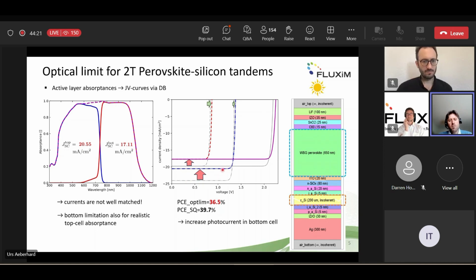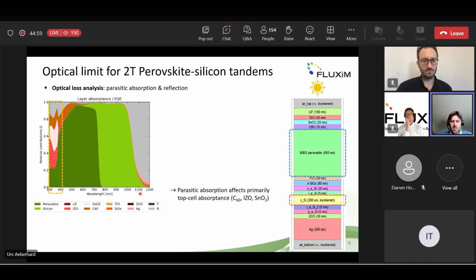This deviates from the Shockley-Queisser detailed balance limit due to the different absorptance. First of all, the top cell short circuit current is reduced, but also the one from the silicon due to the finite absorptance here. So you have a slightly lower PCE, but also you have this problem with the bottom limitation. So you want to increase the photocurrent in the bottom cell. This is the first thing you should do. And in order to see how one can do that, we need to look at the optical losses.